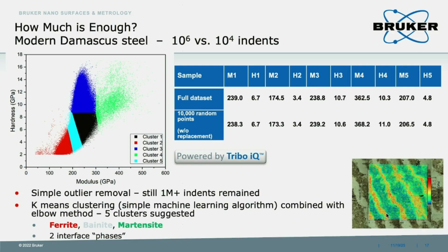Okay, so we got a question from the customer. Do we need 1 million indents every time? Of course not, right? 1 million is time consuming. So we pick 10,000 indents from the 1 million indents. So we use the Tribo IQ to run the 10,000 data. You can see the values for each phase are very correlated, almost the same. This gives us the idea: how much data is enough? Maybe 10,000, maybe 8,000, 7,000 is enough. You can try, because Tribo IQ is very fast. It can output and analyze data within minutes, within seconds, right? So you can do a lot of different analysis. The key is that you already have the raw data here. So this will help your research in a more efficient way.